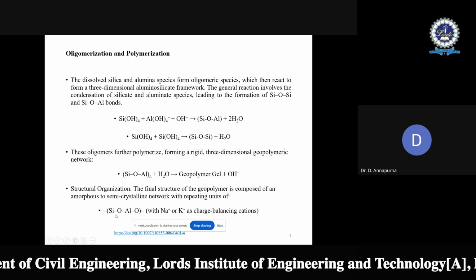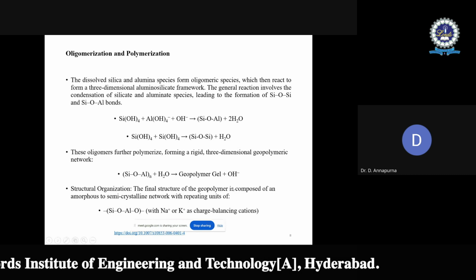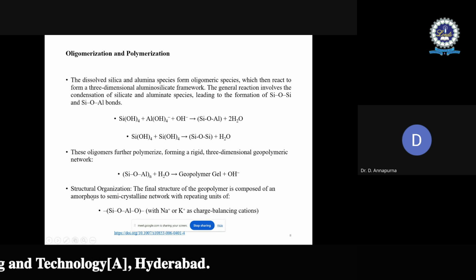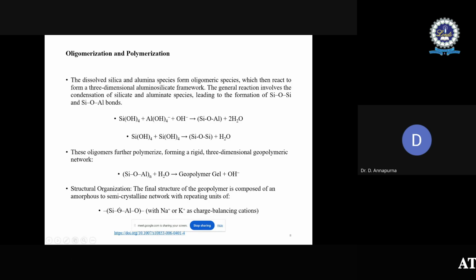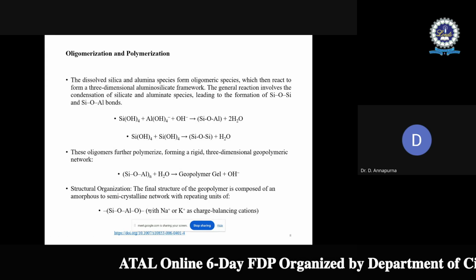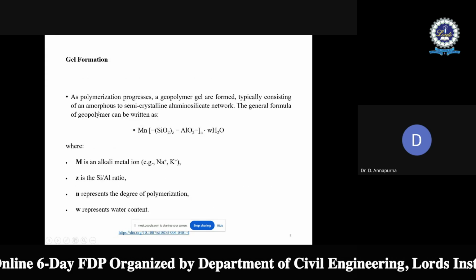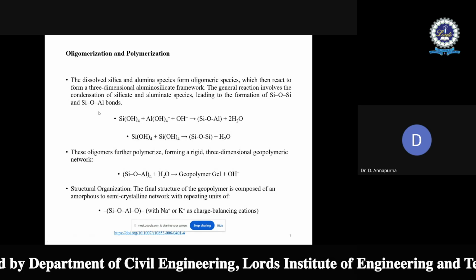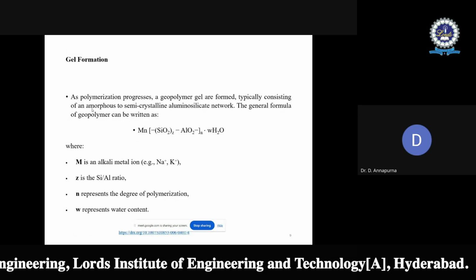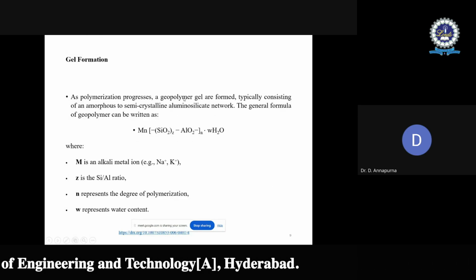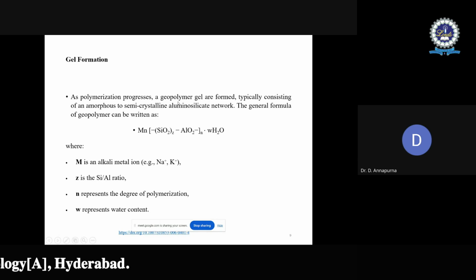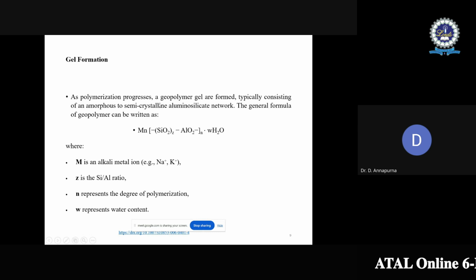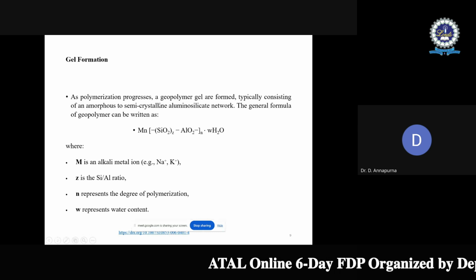So in this structural organization, the final structure of the geopolymer is composed of an amorphous to semi-crystalline network with repeating units like silica, oxygen, alumina, oxygen. So in terms of repeating structures, the final structure will be formed. Then the gel formation. After this polymerization, the gel formation does occur. As polymerization progresses, a geopolymer gel is formed, typically consisting of an amorphous to semi-crystalline aluminosilicate network. Now it is converting into a semi-crystalline aluminosilicate network.